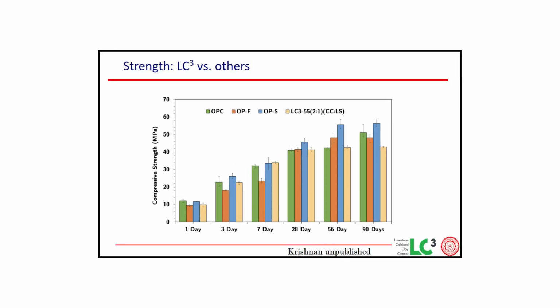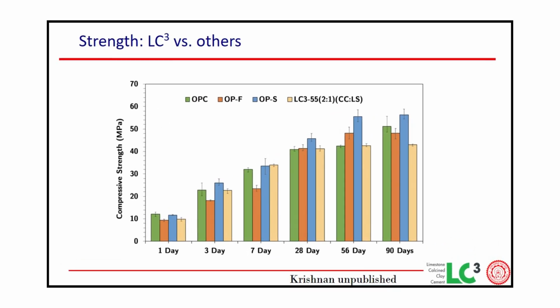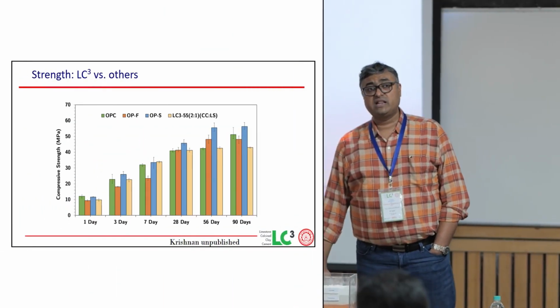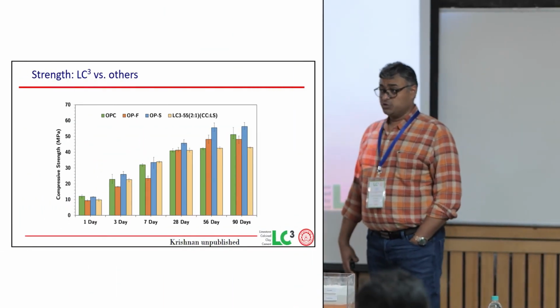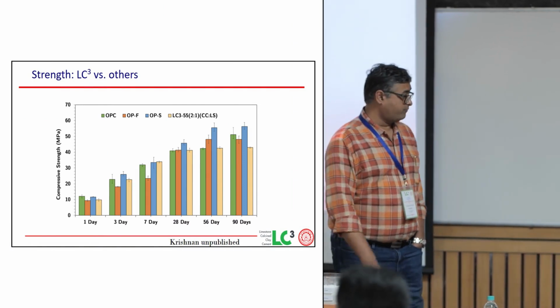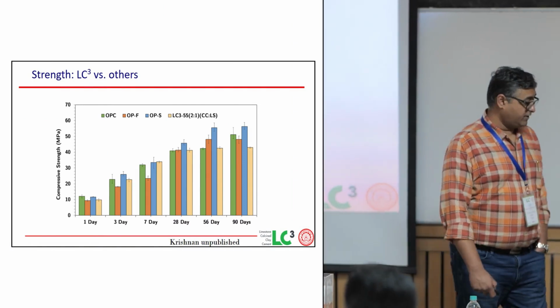The idea of LC3 was that despite having only 50% clinker or even lower, we saw in the initial results 12 years ago that the strength at 28 days was similar to OPCs with clinker of 90%. And that was very encouraging. That forced us to go forward and study the cement further.